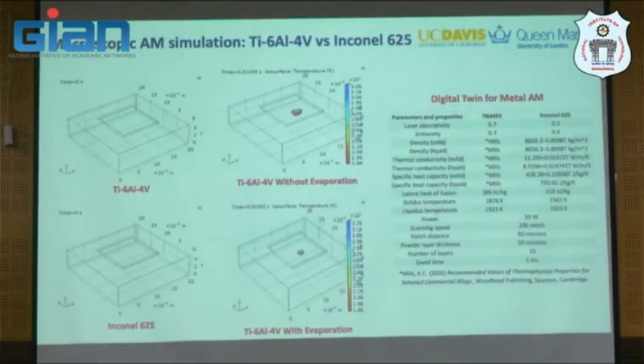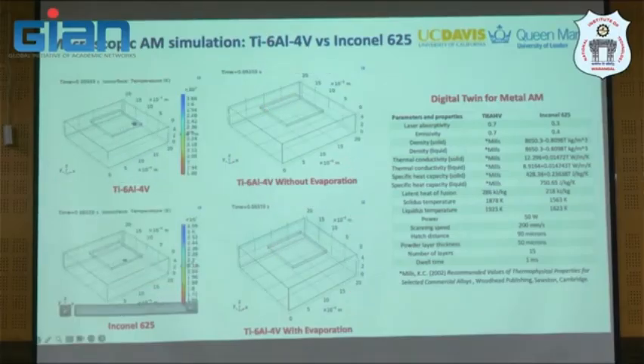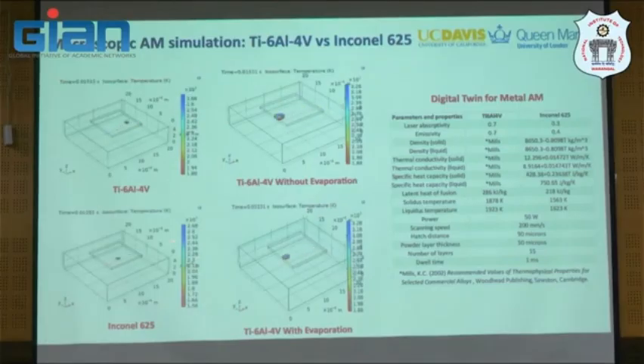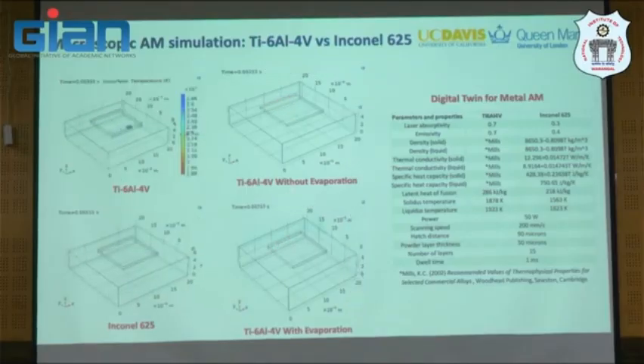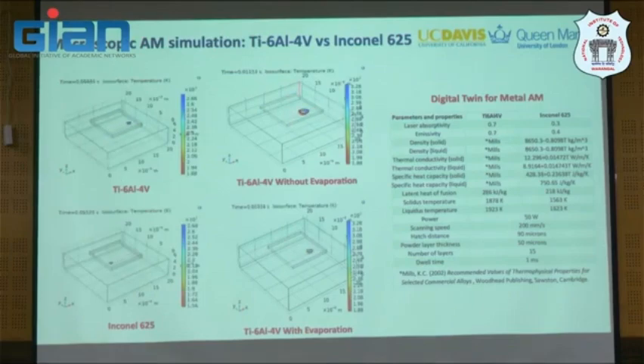And now we try to test something on two systems, on the titanium-64 and Inconel 625. Using the property on the right-hand side, you will see that this is a temperature-dependent property, as well as for titanium-64 from the literature identified here. It's quite big, so we don't put it here. But if you look at Ti-64 and Inconel 625, there will be some differences in the size of the melt pool for sure, because yesterday we talked about how different thermophysical property contribute to different heat, diffusion, conduction, and convection in your domain. And if you have without evaporation, that means you overestimate the temperature field, and your melt pool is actually bigger than with evaporation.